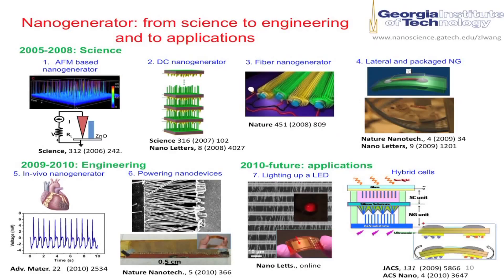Today we make the device about a fingertip size — one centimeter square and 10 microns in thickness. We can generate a continuous microwatt output, 10 to the minus 6 watts output.